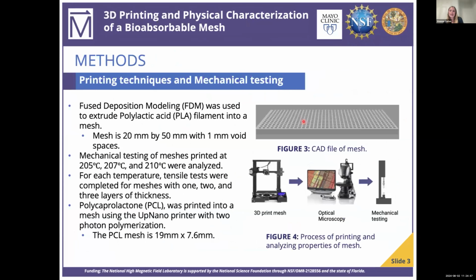So to do this, we use fused deposition modeling, and we extruded PLA filament into a mesh. So figure 3 shows the CAD file that I used of the mesh. And then we did mechanical testing at 205, 207, and 210 degrees Celsius. And then at these temperatures, we printed 1, 2, and 3 layers, with each layer being 0.25 millimeters. And then we also printed PCL using photon polymerization using the UpNano printer.